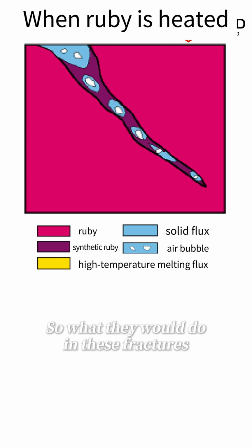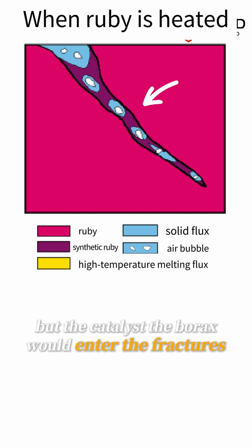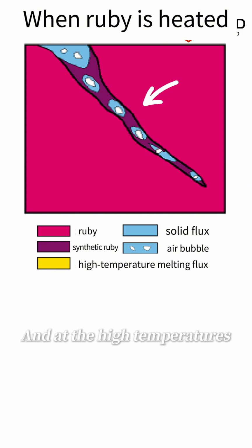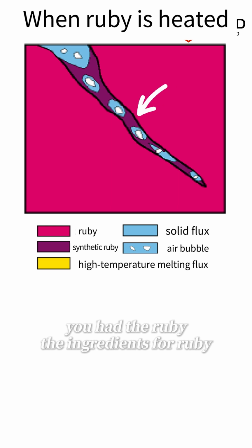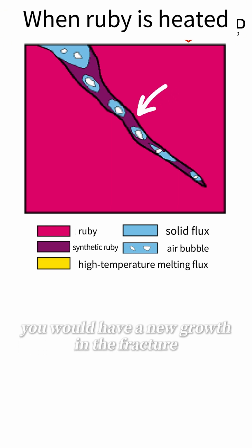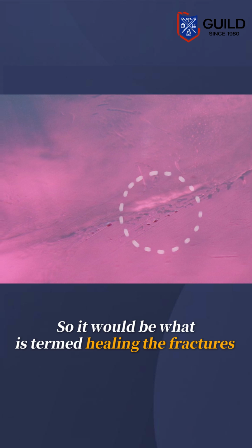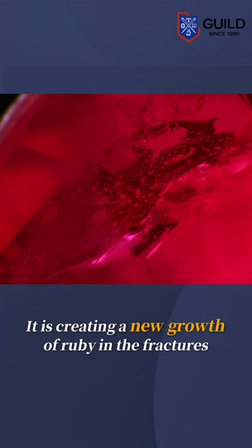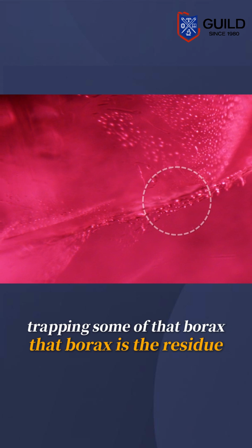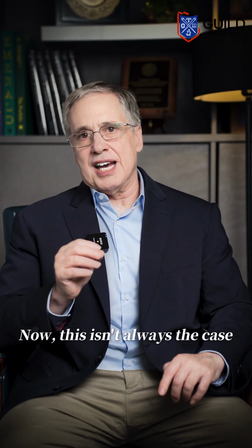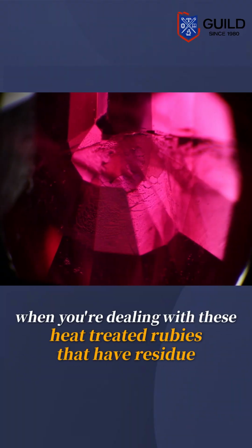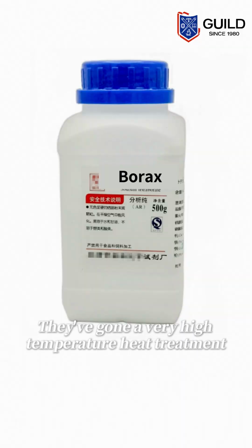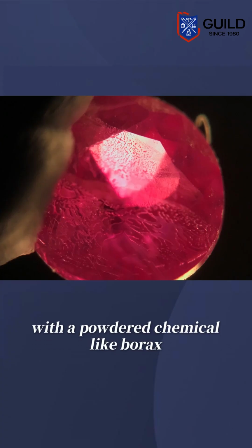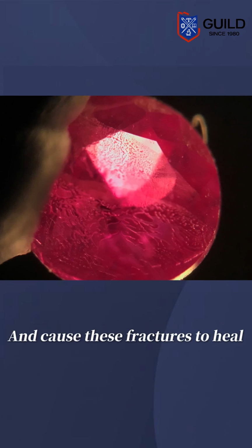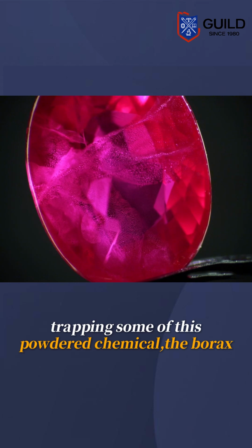So in these fractures, they did not fill them, but the catalyst, the borax, would enter the fractures, and at the high temperatures, you had the ingredients for ruby, so you would have a new growth in the fracture. So it would be what is termed healing the fractures. It's not filling them. It is creating a new growth of ruby in the fractures and trapping some of that borax. That borax is the residue. Now, this isn't always the case, but a lot of times when you're dealing with heat-treated rubies that have residue, they have undergone a very high temperature heat treatment with a powdered chemical like borax that causes these fractures to heal, trapping some of this powdered chemical, the borax.